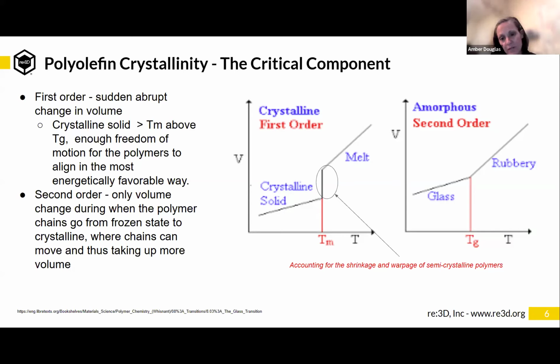That is different, because with the amorphous polymer, you only really have the Tg, and then that pretty much is the rubbery polymer after that, and it gets softer and softer until it becomes a liquid and eventually decomposes with increasing heat. What you see with crystalline polymers that you don't see with amorphous polymers is this big jump in volume. So the shrink rate is quite a bit more than you'd ever see with an amorphous polymer. You can see that in that diagram right there, the first order crystallinity.